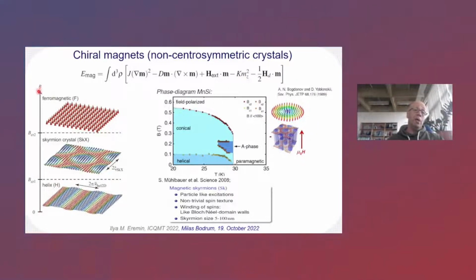If you change the applied field, you start from a helical phase and you reach, upon saturation field, the ferromagnetic arrangement. But there is also another phase in between, which is a skyrmionic crystal, which is thermodynamically stable, in contrast to single skyrmions, which are usually metastable objects. And they were successfully realized by Mühlbauer et al. in 2008. For the sake of the story, one has to remind that this A phase had indeed been seen in MnSi. This is a system which can, to a first approximation, be described by this Hamiltonian. The presence of the A phase was known for some time, but Mühlbauer was the first to successfully show that this phase corresponds to the skyrmionic crystal.